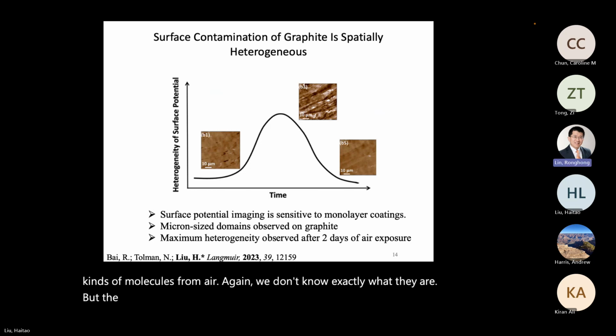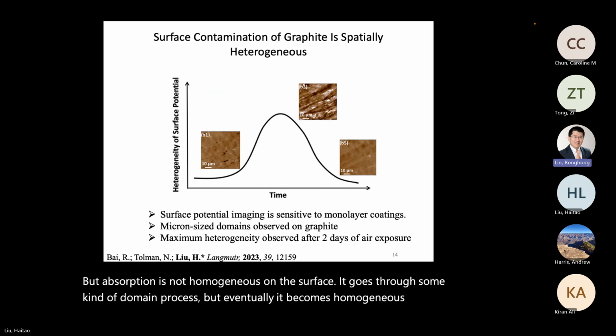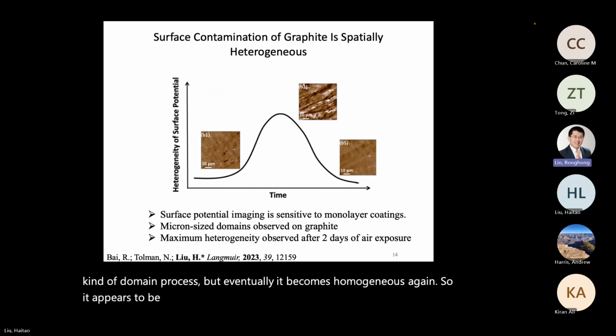But the absorption is not homogeneous on the surface. It goes through some kind of domain process. But eventually, it becomes homogeneous again. So it appears to be some kind of dynamic replacement, which is not really surprising.